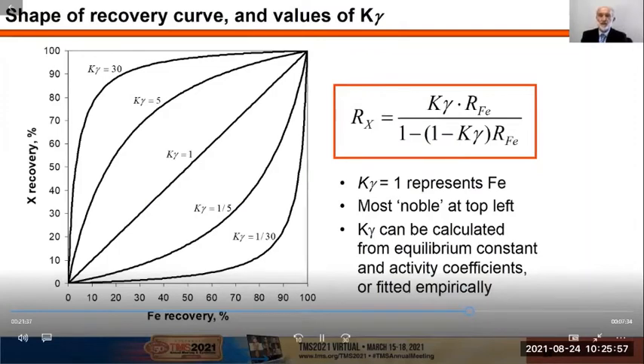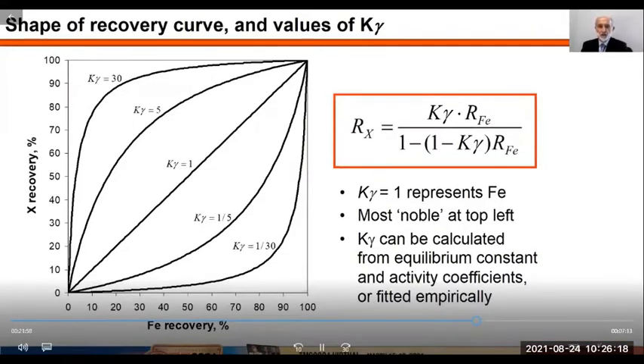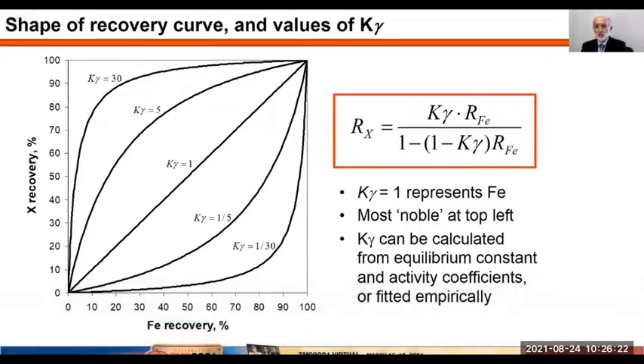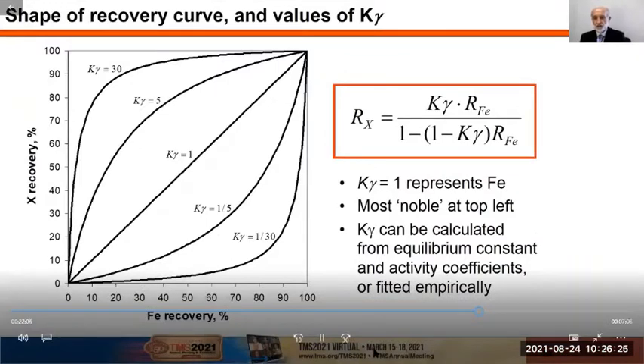This equation can be plotted out for any of the metals, doesn't have to be only nickel. So for metal X, we have drawn a series of curves at various values of K gamma, and you can see that a straight line representing iron versus iron is K gamma equals 1, the 45-degree line in the middle of the curve, and the curves to the upper left represent the more noble and the least noble at the bottom right. K gamma can be calculated from equilibrium constant and activity coefficients, or it can usefully be fitted empirically with a single value that matches a recovery of nickel to recovery of iron under a set of conditions. This makes it quite a powerful predictive technique.